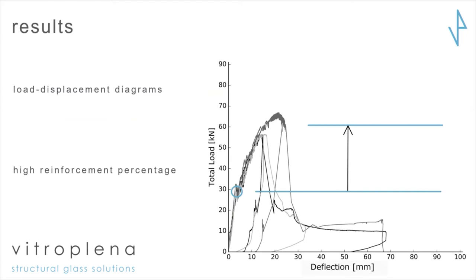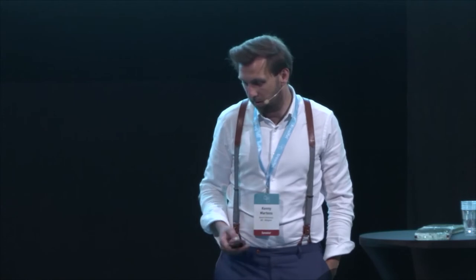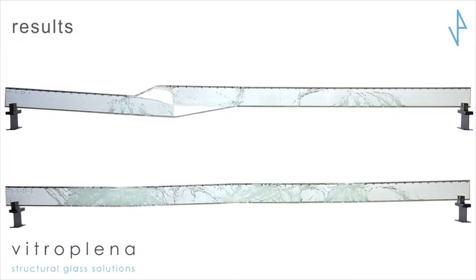These are the results for the solid reinforcement — just the same size but the entire section is filled, not hollow. After fracture we can get really high levels, but at that zone we don't have a real long plastic plateau. That was because the resin we used was too weak to further transfer loads and make the reinforcement yield — so we had bonding failure there. But still, you have a post-fracture capacity more than double the glass fracture load, so it's very safe.